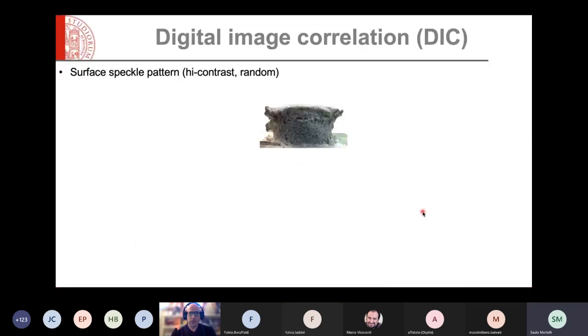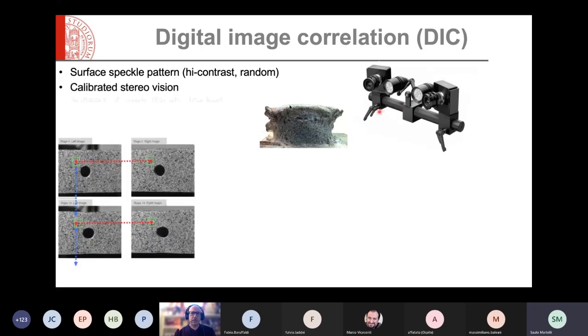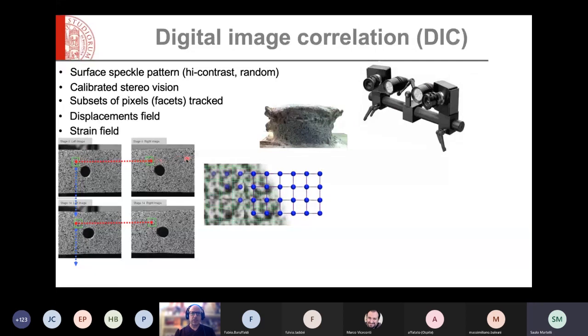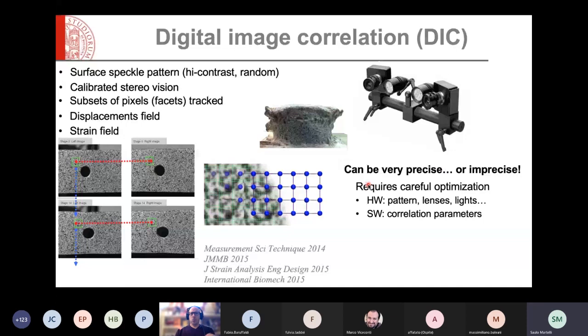So we were very happy when a new technique came, digital image correlation, which requires a contrast pattern, black and white on the surface, and cameras acquiring a calibrated vision so that you can monitor subsets of pixels and see how they move, and by deriving you can compute the strain distribution. It can be very precise or very bad depending on how you use it. If you do careful optimization of the hardware and software parameters to obtain the minimum error, you can achieve a positioning error, an error in the measured position, of the order of 1 micron on a specimen of the size of one large bone, and strains can be measured with a precision of around 100 microstrain, where the main source of error is typically noise.